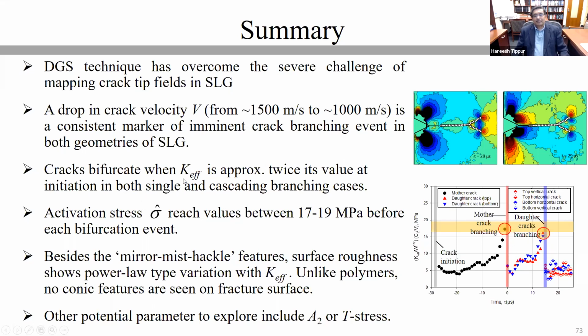Crack bifurcates when effective stress intensity factor is approximately twice the value at initiation, and the sigma hat reaching a consistent value of 17 to 19 megapascals. And mirror, mist, Hackle regions are seen, but we don't see any conic marks. And one place that we still need to explore is how do we go about evaluating the T-stress in order to explain our phenomenon a little bit better, particularly in terms of the crack branching angles, etc.